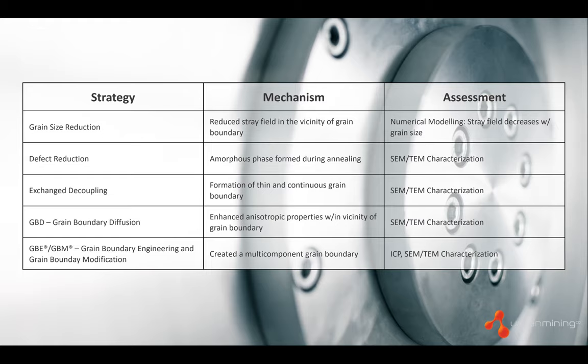And so then the focus became, how do we reduce defects in order to make that microstructure as uniform as possible during the annealing stage? Well, that hit a plateau at some point. Then the next evolution was, how do we fine-tune the grain boundary? Because the discovery in the literature was that a thin continuous grain boundary that surrounds all of the grains of the magnet material would mitigate the negative effect exchange decoupling could have on remanence when you're annealing the product. And so that became a term of art in that time. And then in 2007 and 2008, you had grain boundary diffusion, which was an invention introduced by Sagawa.